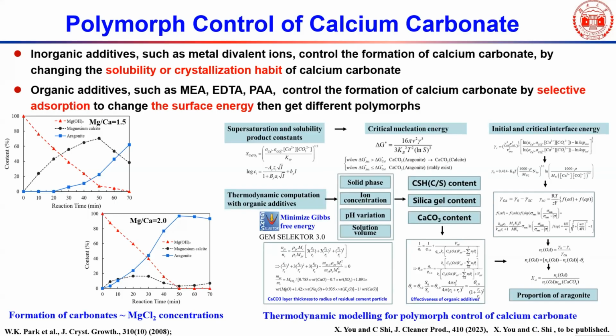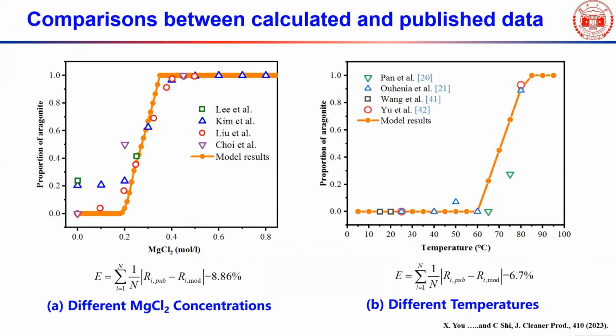And we also tried some organic additives such as MEA, EDTA, and PAA. They can control the formation of calcium carbonate by selective adsorption to change the surface energy, and then get different polymorphs. So those thermodynamics can really help guide our research and achieve different results.